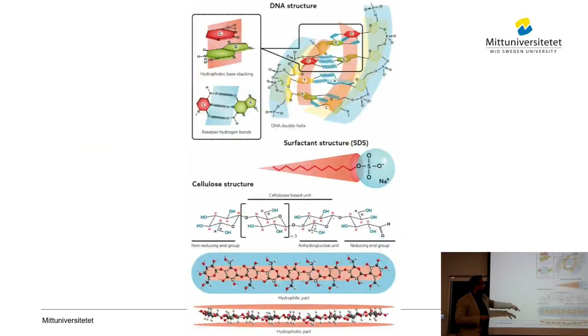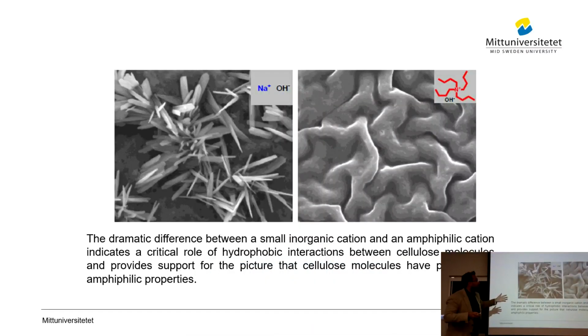And just so this picture, I should have checked your presentation before. You clearly see the spatial asymmetry where you have these hydrophobic and more hydrophilic areas, somehow similar to surfactants, and eventually to other molecules such as DNA, where you have these different amphiphilic regions. And therefore, you have to consider hydrophobic interactions for sure, for the dissolution, also for degradation. You cannot neglect that.